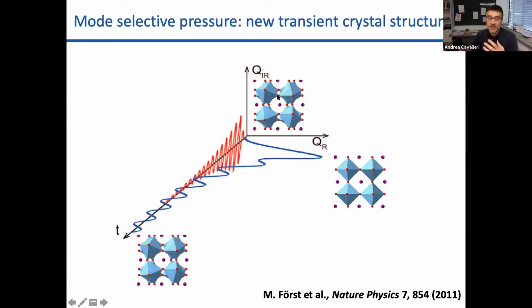second mode. So I will create a crystal structure that is not stable at equilibrium and that is only created as long as the first phonon is being driven, by virtue of the fact that work is being done on the system. And so one can use this method to design crystal structures in ways that can expose new physical properties that I would not have at equilibrium. And this can be done selectively.